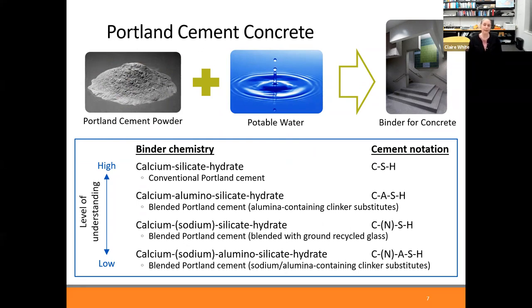However, it is known that the main phase that gives concrete strength is called calcium-silicate-hydrate gel. And so this calcium-silicate-hydrate gel, people have looked into quite a lot over decades and decades. And so we have quite a good understanding of CSH gel. And this is cement notation because we have so many elements. The cement community has a cement notation. This is not carbon, sulfur, hydrogen. This is calcium silicate hydrate. What's happening now, as we're trying to reduce the amount of Portland cement powder we need to make a certain amount of concrete, is we're adding in other materials.